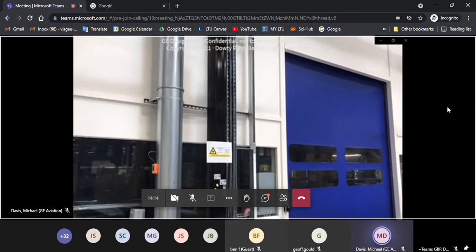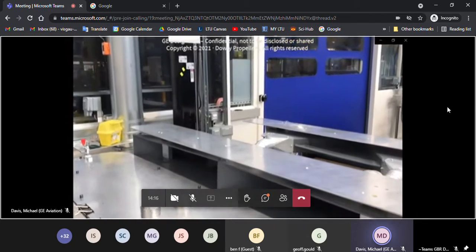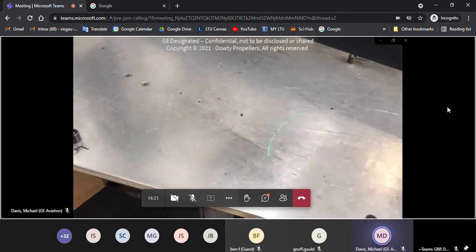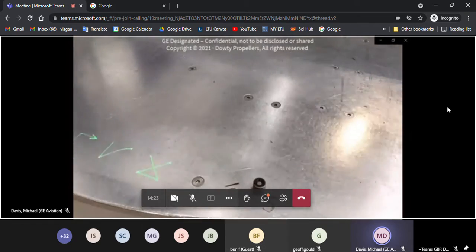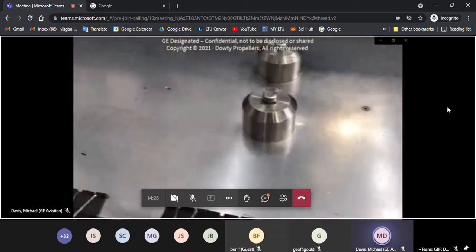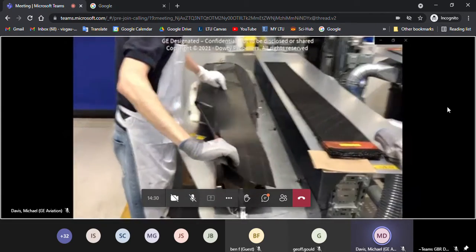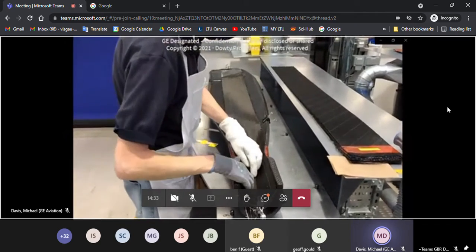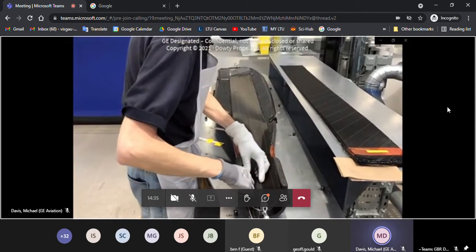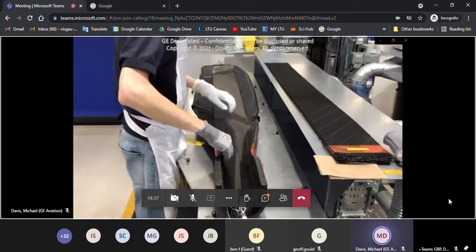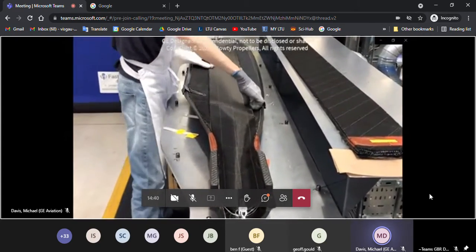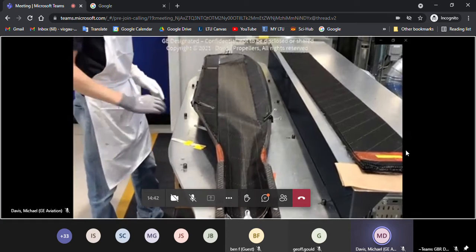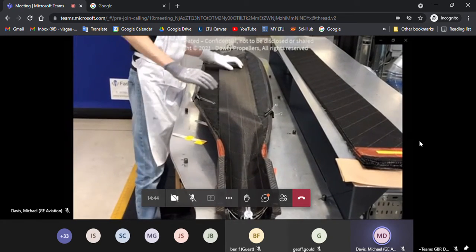Here you can see the laser projectors that we have fitted to each of the preforming stations. And you can see the laser pattern being projected down onto the preforming table there. So the preform tool is not located in there, but you can see how the laser patterns are used to locate plies. Now you can see an operator laying up the dry plies into a propeller blade preform. So he's locating them using the laser pattern, which you can just see on the edge of where he's locating